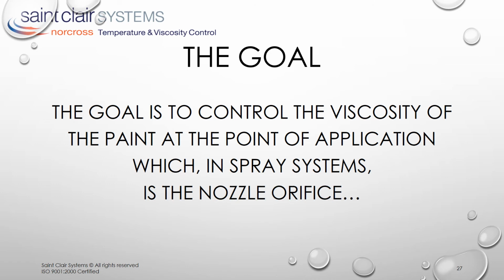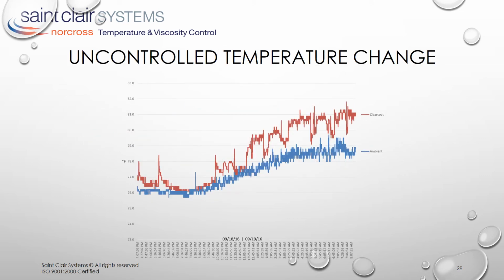The real question is, does the temperature of the paint really change all that much? We expect a paint system with no temperature control to display a temperature variation, and here we can see just that. The clear coat temperature actually increases by a full 5 degrees Fahrenheit, whereas the ambient only increases by 3 degrees Fahrenheit. The remaining 2 degrees is due to other factors we talked about, primarily friction caused by shear.